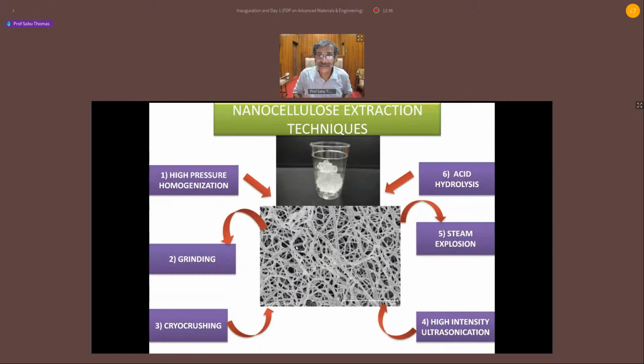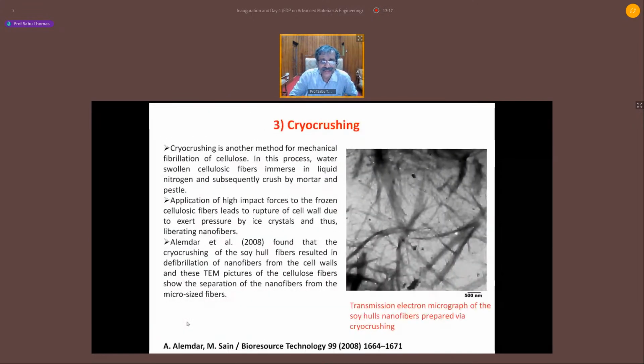Then you might ask, how do you produce them from plants? You can do acid hydrolysis. You can do steam explosion process. You can do high intensity ultrasonication process. You can do high pressure homogenization process. You can do super grinding invented by the Japanese people. You can do cryo crushing. You subject the fiber under low temperature and you go for crushing. So in all these processes, what we do is you apply intense shear to the system and then you remove lignin, hemicellulose and split up the fiber. These are all well-known techniques. I will show you what we do in our laboratory.